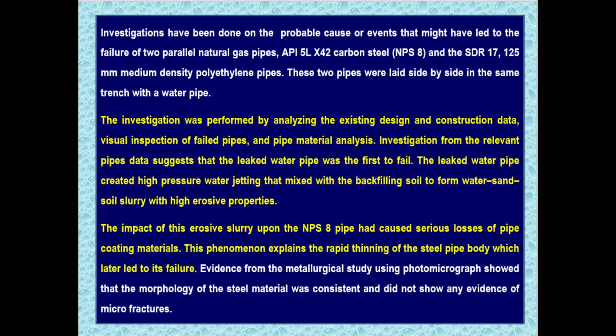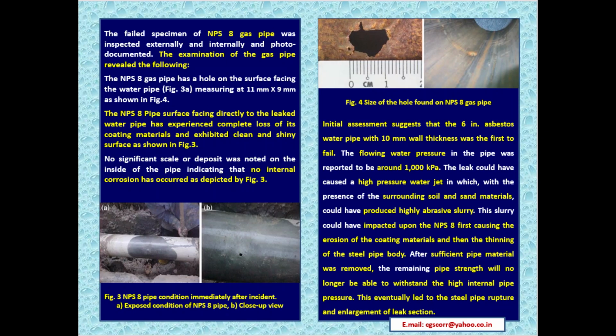Evidence from the metallurgical study using photomicrograph showed that the morphology of the steel material was consistent and did not show any evidence of microfractures. The failed specimen of the NPS 8 gas pipe was inspected externally and internally and photo documented. The examination of the gas pipe revealed the following. The NPS 8 gas pipe has a hole on the surface facing the water pipe.